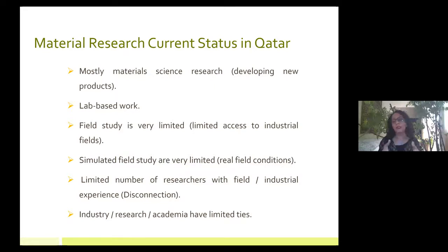And so Alan and I were looking at testing samples in their as received condition. We don't grind them, we don't polish them, we look at them, and then we grind and polish the samples and we do the testing. What we found both is that the results are different. When you prepare your sample with a nice, clean, polished surface, it's completely different than when you use it as received, because cracking usually initiates with pits, and these pits occur on the surface. They are associated with your residual stresses. So when you grind and polish, sometimes you add residual stresses on the surface. So your condition is changing. And if you look at the equipment in the field, they're not ground and polished. And so the as received condition represents the exact real case in the field.